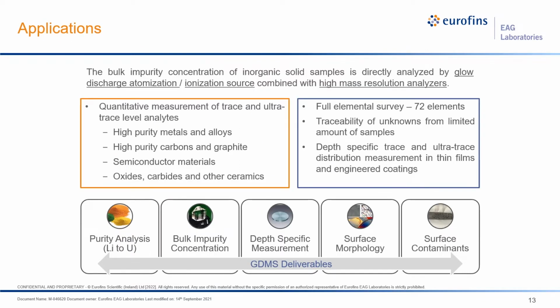The major application of GDMS lies in the fact that the glow discharge atomization and ionization process, combined with a high mass resolution analyzer, can provide bulk impurity concentration of inorganic solid samples. Specifically, it can provide quantitative measurement of trace and ultra trace level analytes in materials such as high purity metals, alloys, high purity carbon, graphites, semiconductor materials, oxides. And it is a full element survey. It can establish traceability for unknowns from a limited amount of sample. And it can also provide depth-specific information.